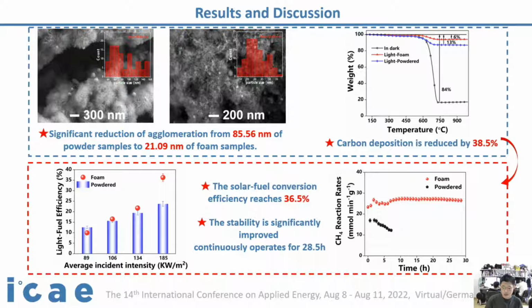As a result, there is a significant reduction of agglomeration from 85.56 nanometers of powder samples to 21.09 nanometers of foam samples, which caused the carbon deposition to be reduced by 38.5% at the same time. The solar to fuel conversion efficiency reaches 36.5% for the foam samples, and it continuously operates for 28.5 hours with significantly improved stability.